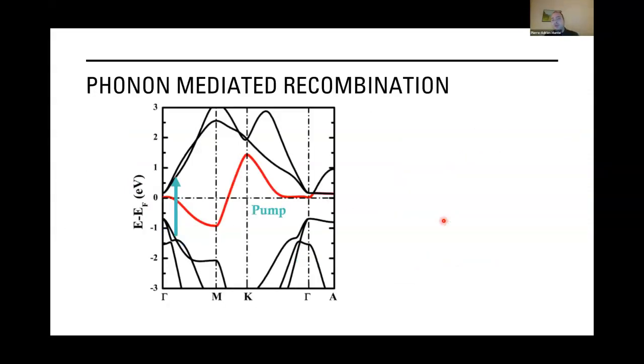First of all, if we look at the band structure of our material in the undistorted phase, the particularity of this tantalum disulfide and other transition metal dichalcogenides is that there is a band that is straddling the Fermi level. So when we excite with our pump, we are going to generate electrons from this sulfur dominant orbital into some tantalum orbital.